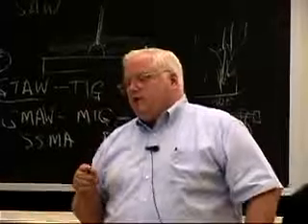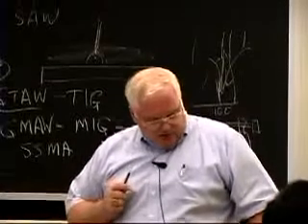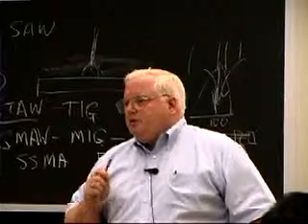I don't know base metals here. I do know cast alloys that would be in that range. The 5000 series are aluminum magnesium alloys, and essentially get their strength by just solid solution strengthening with 5% or so magnesium in there. The 6000 series alloys, which are not on there, basically are aluminum magnesium silicon, and they're heat treatable.